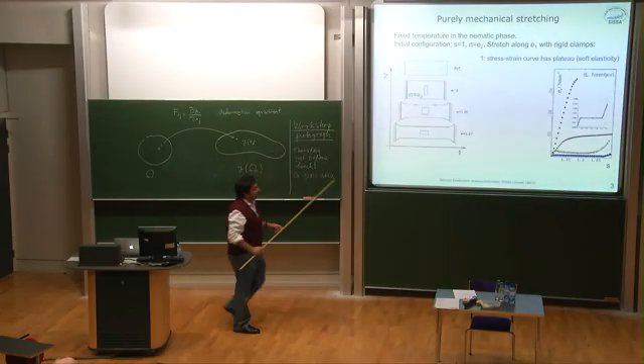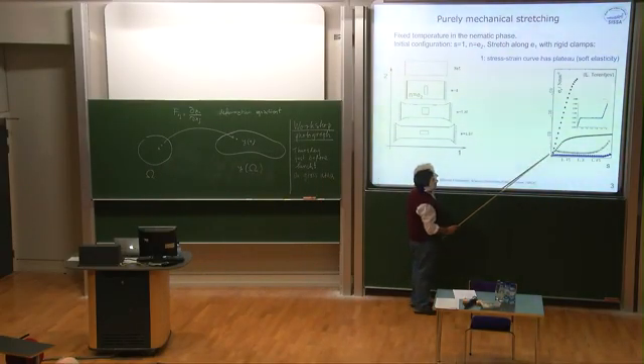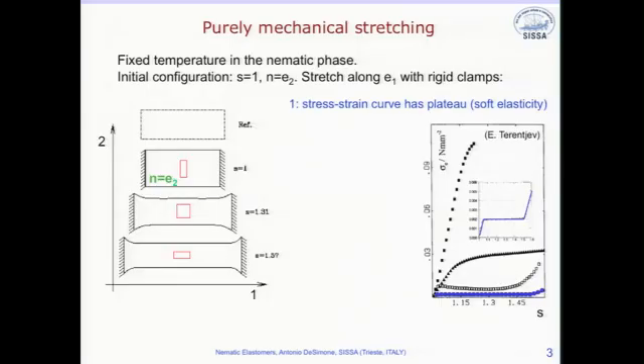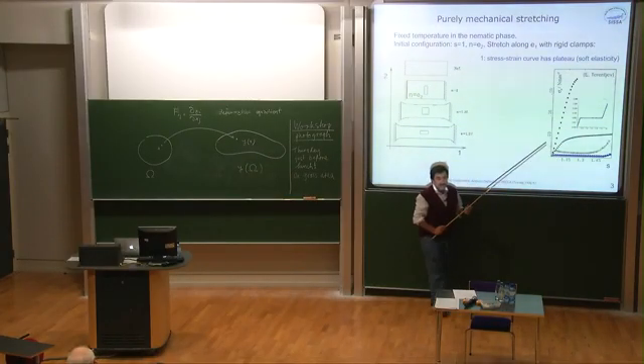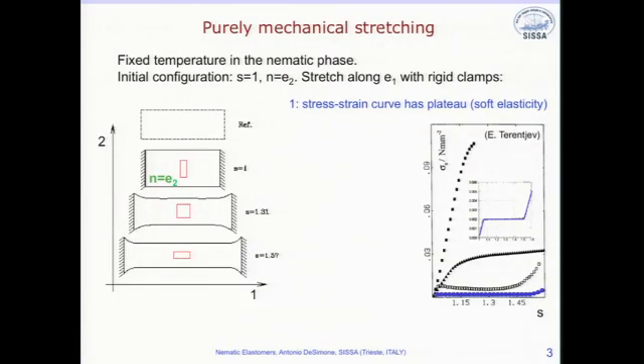Now if you look at the signatures of this in the mechanical response, this is a typical response of a rubber specimen of this kind, which doesn't have these special properties. And this is the way this system would respond, thanks to this internal degree of freedom. Here is a blow up of this that shows that there's an initial part of standard behavior, then a threshold where something interesting is happening. Here there's a knee between two completely different responses. There's a plateau, and then again the standard behavior. Like in a phase transition, the phase transition is occurring here. The orientational degree of freedom is responsible for the nonlinearity in the response.